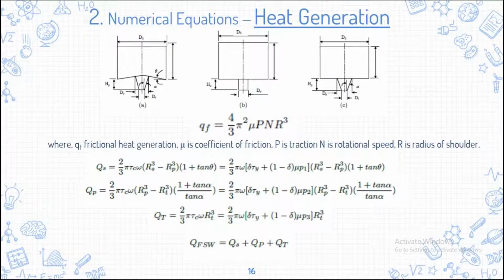So we have developed some numerical equations for heat generation. If you see, this is the tool shoulder diameter, and this is the pin of this friction stir welding tool. So pin diameter and shoulder diameter, and this is the tip of the pin. These three regions of a friction stir welding tool generate heat because of frictional heat. This is the basic frictional heat generation equation. Keeping this as a base, we derived an equation for how much heat is generated at the shoulder.